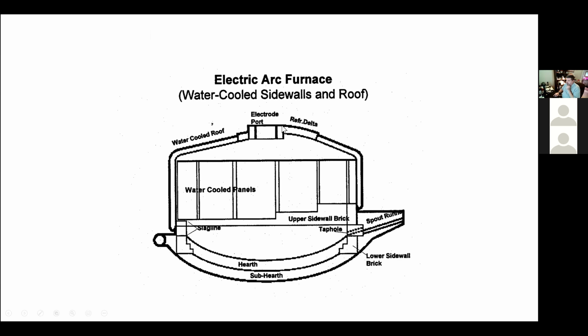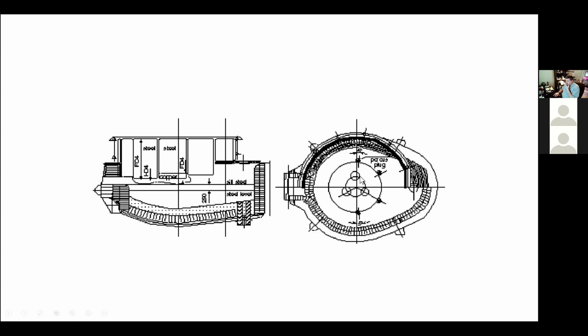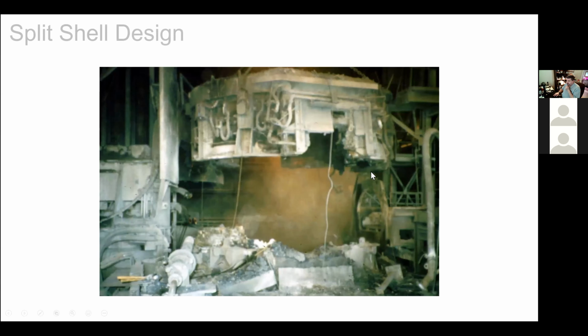We also have, around the electrodes that protrude through the roof, a refractory piece called a refractory delta. And that basically insulates so that we don't arc out directly into the water cooled panels. And this just shows you a plant that's down for maintenance. So they've lifted the water cooled section, the upper shell, clear away from the furnace bottom.